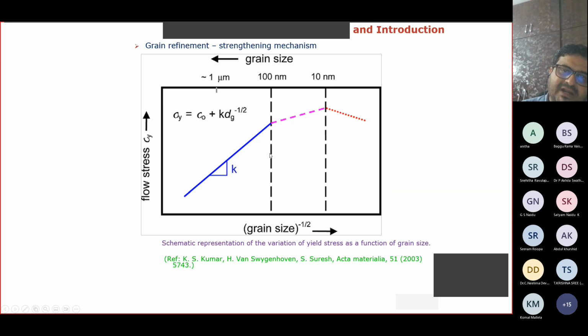And with the grain size between 100 nanometers and 10 nanometers, you also see that the slope is still positive. That means with the decrease in grain size, your strength further increases, but again the rate of increment is different from the rate of increment that you have seen here. And this is because of the change in the deformation mechanism from here to here. Up to here, grain boundaries won't play a major role. It's all dislocations that control the plasticity. But in this regime, in addition to dislocations, grain boundaries also play a major role.